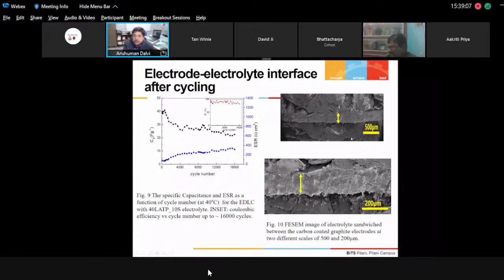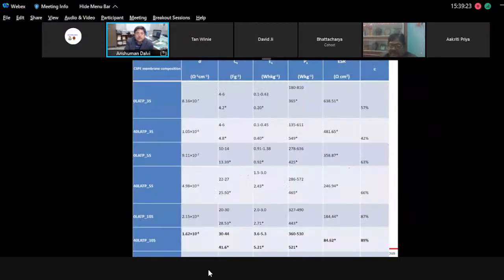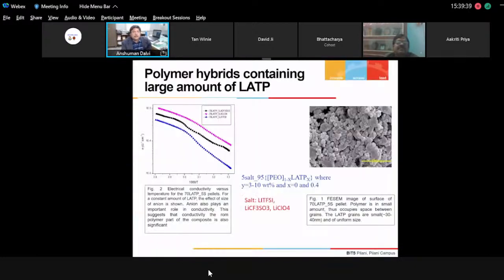And the solid-solid interface, as shown here, is interestingly intact after the 16,000 cycles, and this is also very interesting. The overall parameters, if one sees, are comparable to those of the gels. However, I have to admit that we have to work more on the energy density part, which is a little less, but the power densities seem to be comparable here.